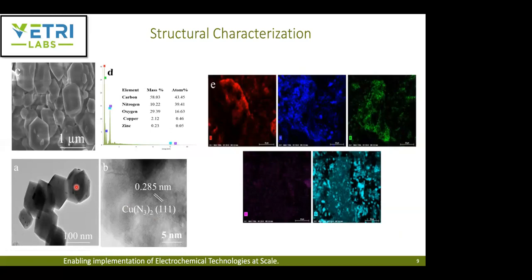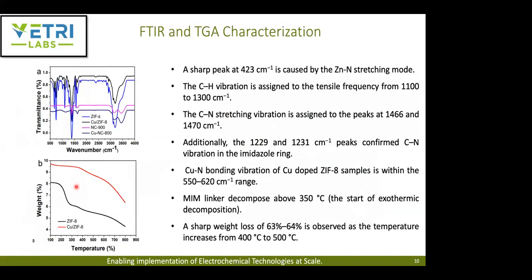So this makes the structure conductive, right, with the copper, and it could also improve the stability of the catalyst, at the same time avoiding the active sites getting directly exposed in the electrolyte. So in turn, you have a good stability. Next, they did the FTIR and the TGA.